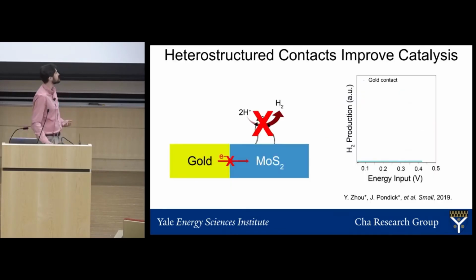But the problem is, at this interface between, for example, gold as a contact material to our molybdenum disulfide catalyst, there's actually a wall for electrons, an energy barrier. So when we push energy into this system to try to make hydrogen, all we're doing is we're trying to push electrons over this wall, which means that none of the energy we put in goes towards making hydrogen. And as a result, you can see for modest applied voltages or energy inputs, we basically get no hydrogen out of this catalyst, which is a problem.